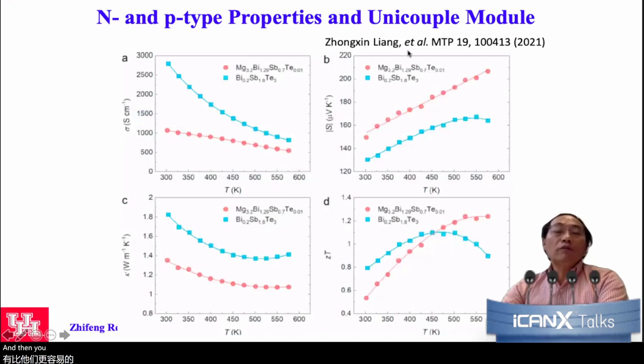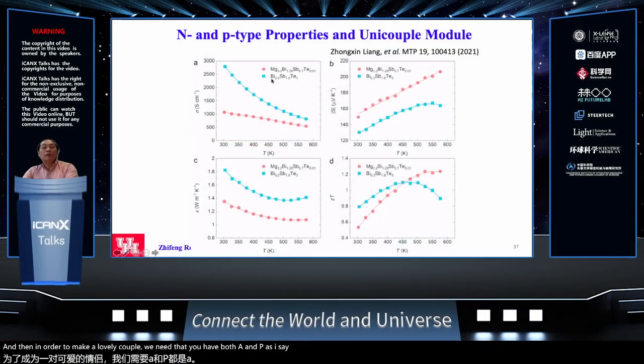And then in order to make a unicouple, we need to have both N and P. As I said, we use the traditional bismuth antimony telluride as the P material, which has a larger electroconductivity. The new N-type material has lower electroconductivity. At the end, the ZT of the traditional material and the new material are comparable within a wide range of temperature.